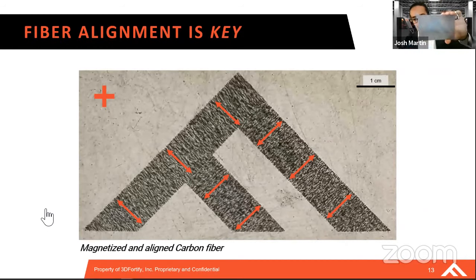And so this is a sample that's printed and reinforced using magnetized carbon fiber. You can see that within each region of the Fortify logo, we have a unique alignment. And this background here actually looks like it's depleted of fiber, but it's only due to the optics of fibers being aligned out of plane. And otherwise, towards your facing view, just to give you a sense of what we can program within a material.